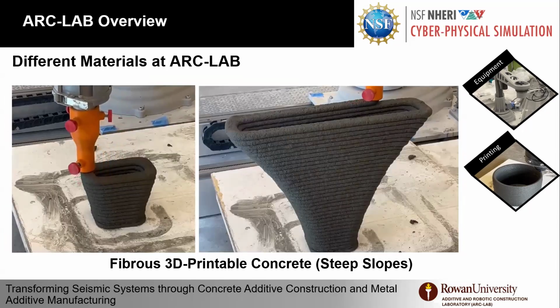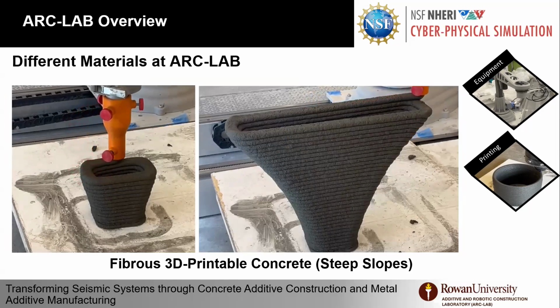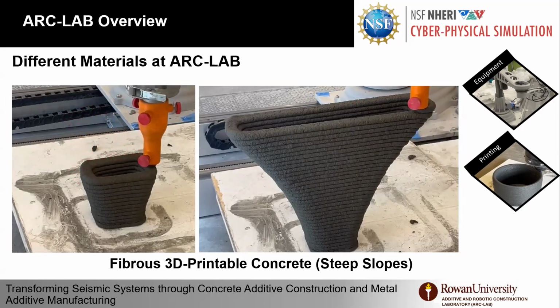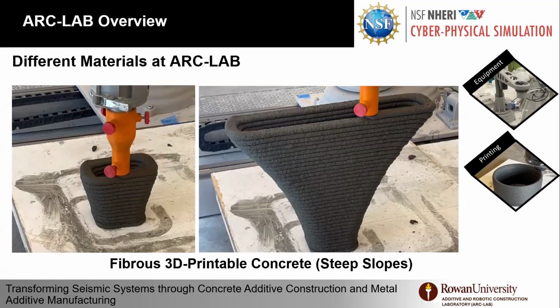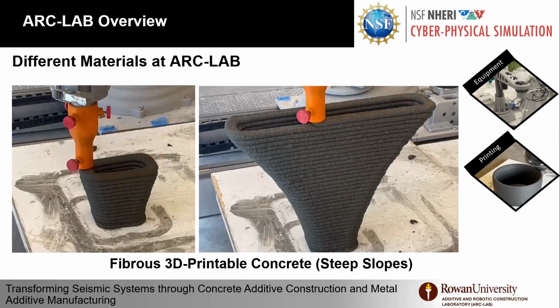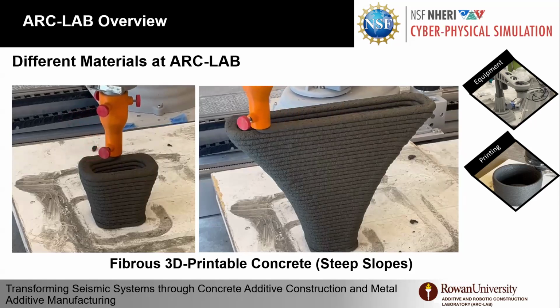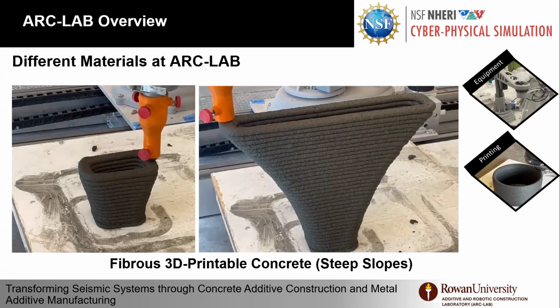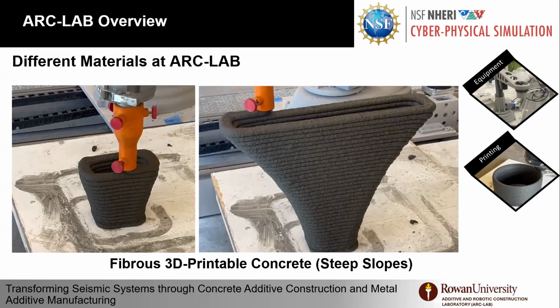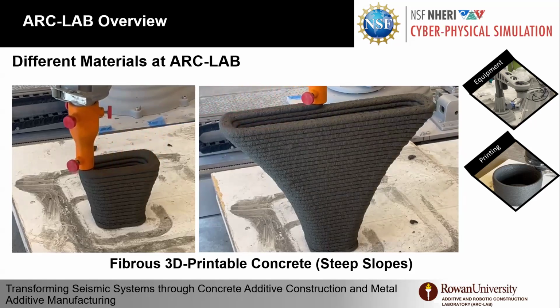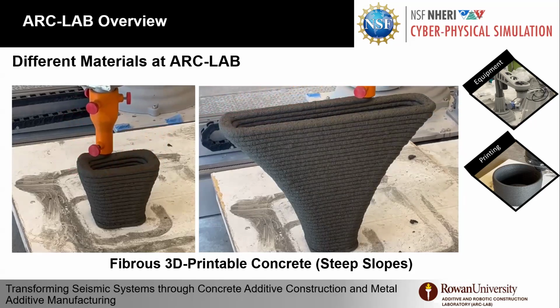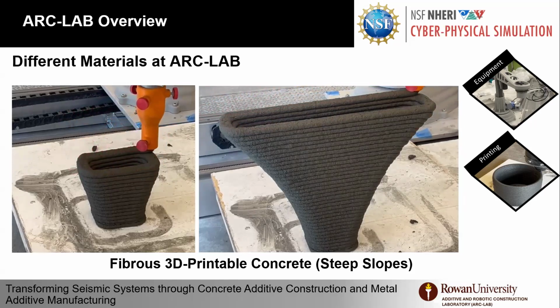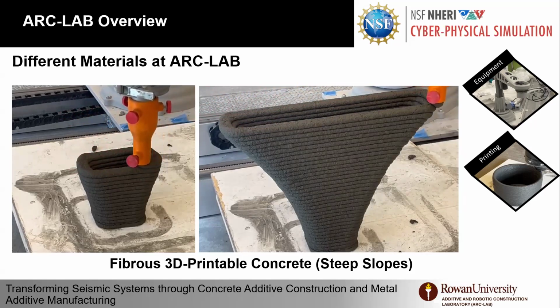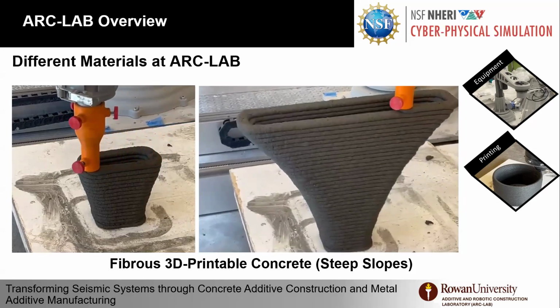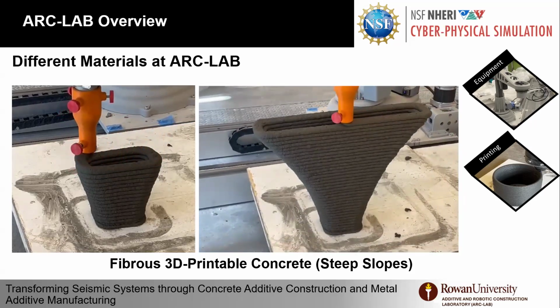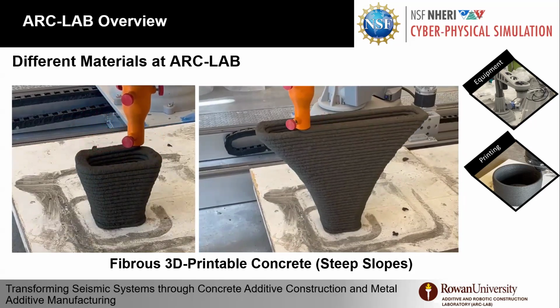We were actually able in our laboratory to print in slopes up to 50 to 55, even 60 degrees from the vertical position. You can see here we start from the base with almost zero slope, and gradually change the slope as we go up. And as you can see here, a lot of material is still fresh, taking about 60 minutes to start setting. So there are a lot of challenges as we print, and a lot of deformation happens in the layers that we don't see, but it's at micro scale. And as you can see here, it's able to withstand the load, especially as the first few layers have smaller dimensions.